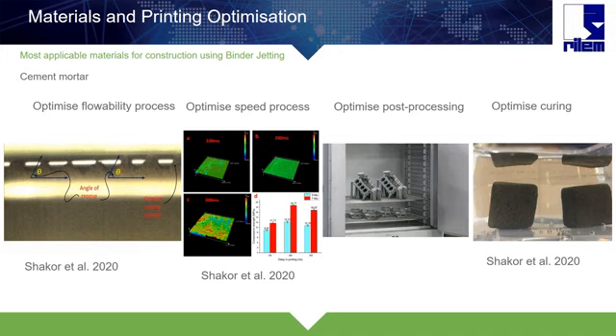However, it's necessary to know as well that post-processing is a major process to be done for each printed material, especially for cement mortar or any kind of material that needs higher strength. It needs to be heated, so the temperature should be elevated in an oven to make the specimens stronger and stiffer.